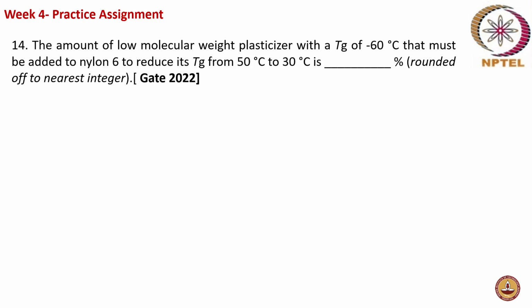The next question. The amount of low molecular weight plasticizer with a Tg of minus 60 that must be added to nylon 6 to reduce its glass transition from 50 to 30 degrees is. So, what is the quantity of some low molecular weight plasticizer having a glass transition temperature of minus 60 that must be added to nylon to reduce its glass transition from 50 to 30 degrees? This is the GATE 2022 question. So, how do you start about this?